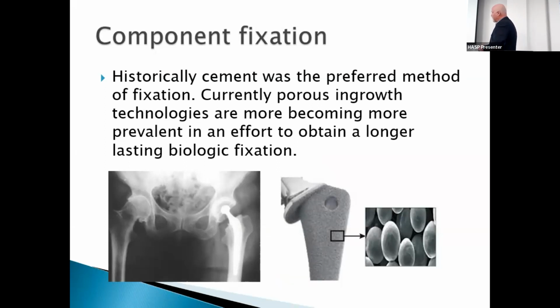There's some thought that one of the concerns in the long run, when you start to talk about 20 to 30 year experience and survivorship, is whether this cement tends to break down over time. And that has spurred the thought of using an implant like this, where it has a roughened metal surface with the surface porosity being very carefully constructed to be optimum for mimicking the porosity of bone, where bone will then grow into these pores and lock the implant into place, giving us a biologic fixation, which is a living fixation, essentially. It can respond and adapt to stress over time, which would hopefully outpace a cement fixation.